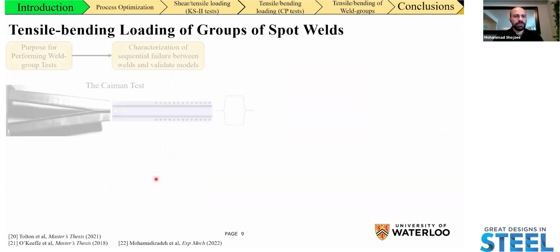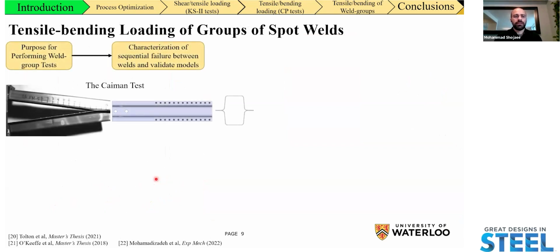Now, in terms of the component tests, there are a few purposes that we would perform component tests. So we would either characterize sequential failure or a progression of the failure between adjacent welds, or we want to validate our models that have been calibrated using single spot weld characterization techniques, such as the lap shear, cross tension, coach peel, or the KS2 test. The component test that we performed is referred to as the Caiman test that was basically suggested at the University of Waterloo. You can see the geometry of this component.